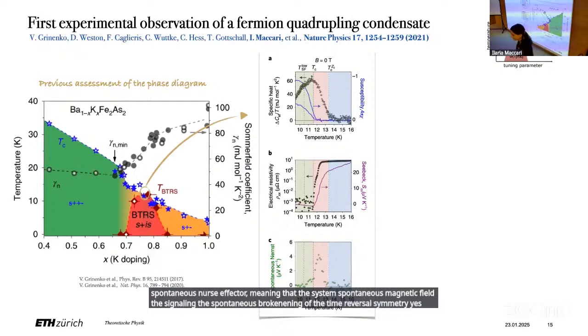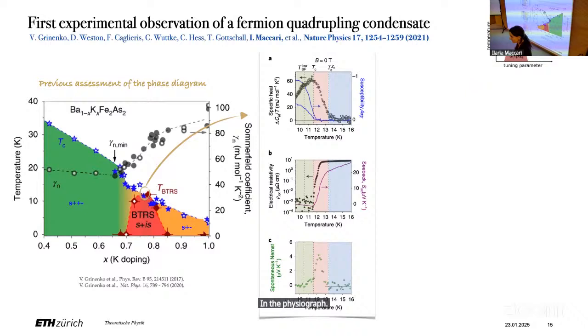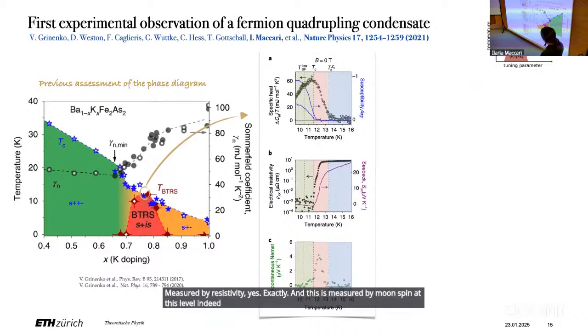Yes? So, in the phase diagram, what are the blue stars? Is this resistivity? Yeah, this is Tc, measured by resistivity, yes. Exactly. And this is measured by muon spin at this level. Indeed, I don't have the picture, but the muon spin measurement also confirmed that time reversal symmetry is broken in this exact regime in temperature.